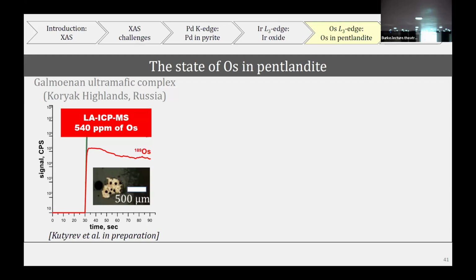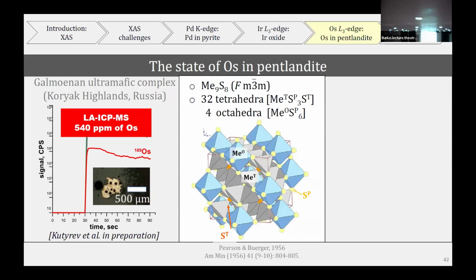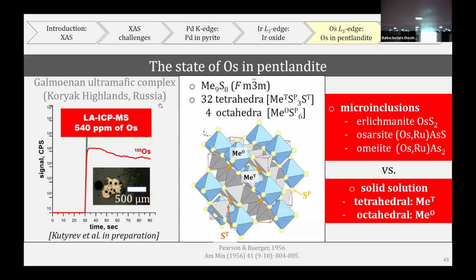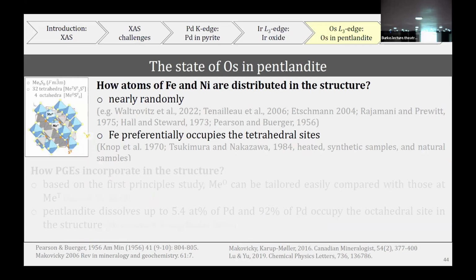So it's a classical, good, easy example, let's say, to study by XANES. The pentlandite structure contains 36 cationic positions. 32 of them are tetrahedral and 4 of them are octahedral. So our preliminary hypothesis could be that osmium incorporates into some kind of micro-inclusions of an osmium-bearing mineral, or it could be a solid solution in the tetrahedral or octahedral positions. Pentlandite is stoichiometric, but the amount of iron and nickel can vary.